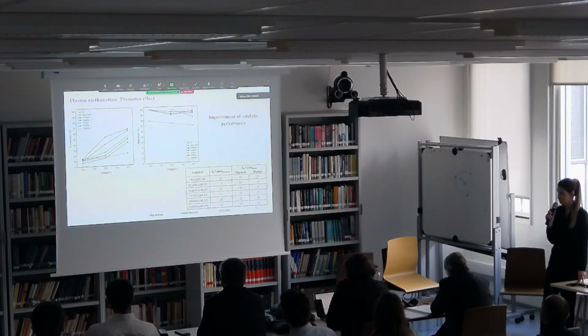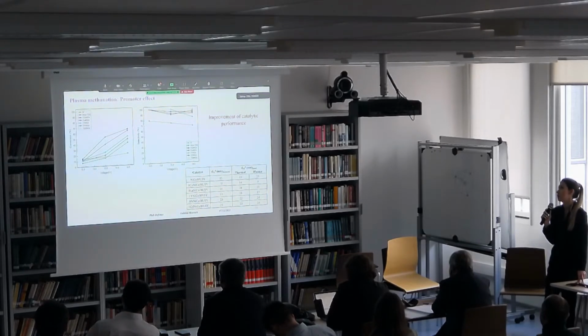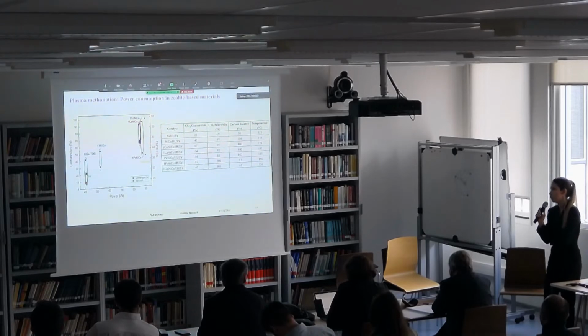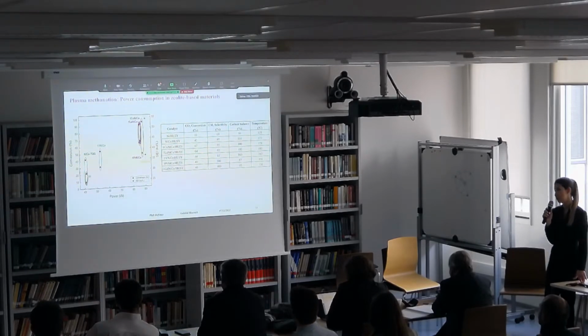Regarding the plasma performance, again, it can be seen that the addition of promoters really improves the catalytic performance, and the selectivity, obviously. Also, cobalt showed the smallest particle size after plasma, and in general, mostly they have different particle sizes after plasma test. Regarding the power consumption, in general for zeolite-based catalysts, the power consumption is higher. While it can be said that probably the yttrium promoted sample has the best catalytic performance, the selectivity is slightly low. But as the carbon cycle is closed, it can be said that the only byproduct is CO.